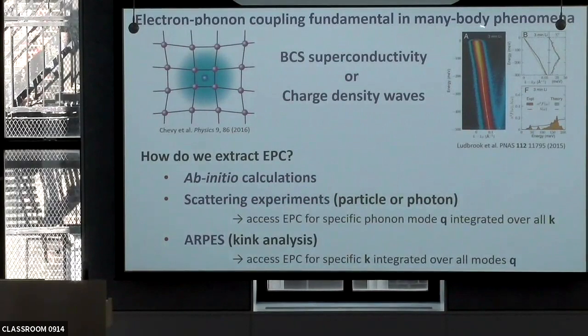In photoemission, often people have looked at a dispersion and the deviation from the bare dispersion due to electron-phonon coupling. This is a case of graphene that we've worked on. And there is the old machinery of using the self-energy, real and imaginary part of the self-energy, to extract the coupling. But that has a couple of problems. The first problem is that when you do this, you're actually integrating over all possible modes in Q.